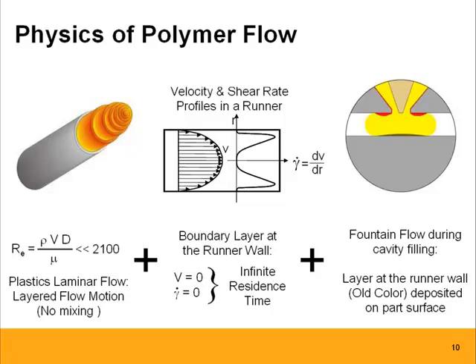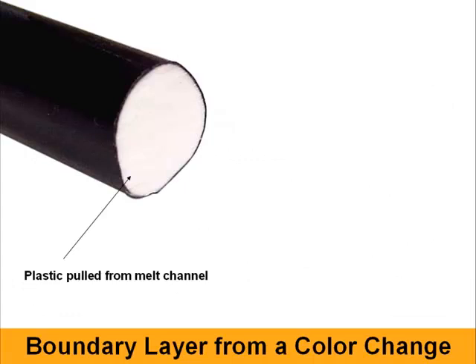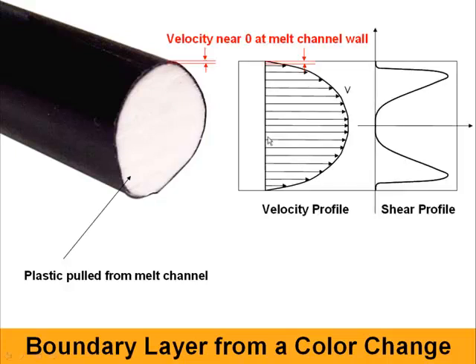This is actually a good example. We pulled one of the melt channels from one of the hot runners after it was cooled down. And as you can see, the theory is supported by reality. What we have here is an outside layer in that melt channel of about 0.3 millimeters. This is all because we were able to push out the inside of the material. 98% is already white, but we have this relatively persistent layer towards the inside of the melt channel. This is very difficult to remove because we have zero velocity in that area.